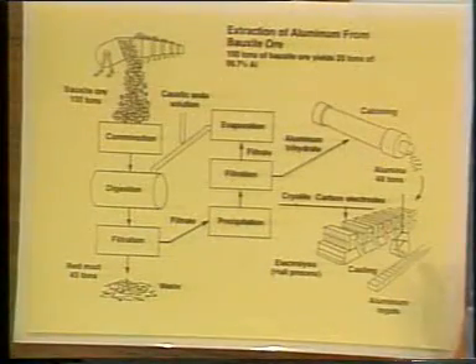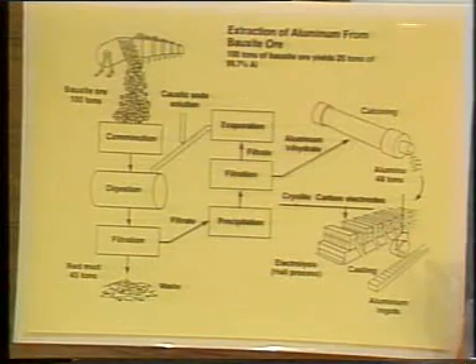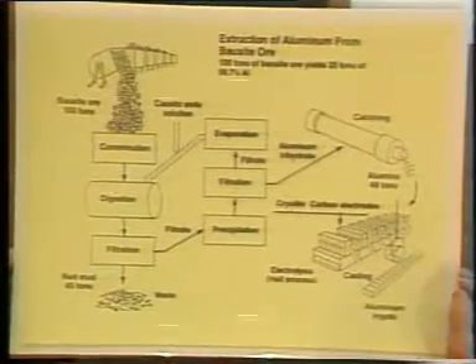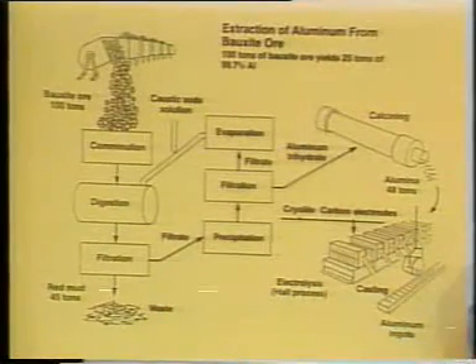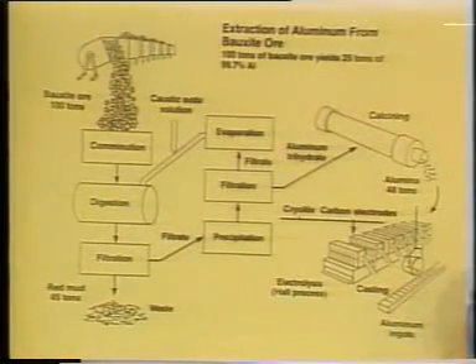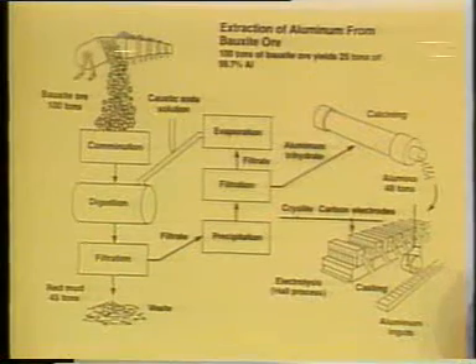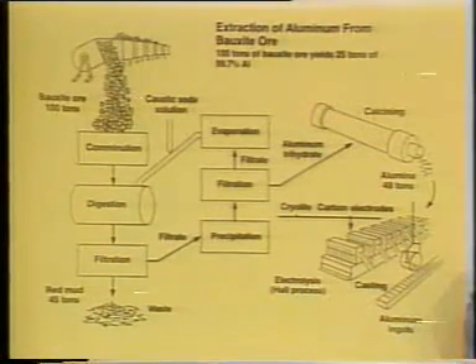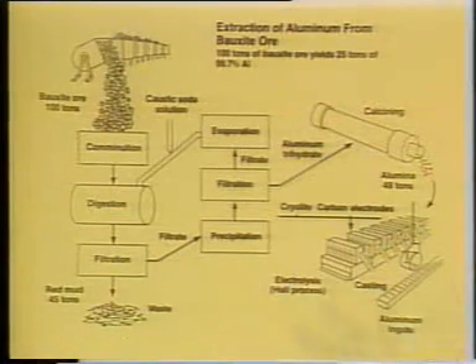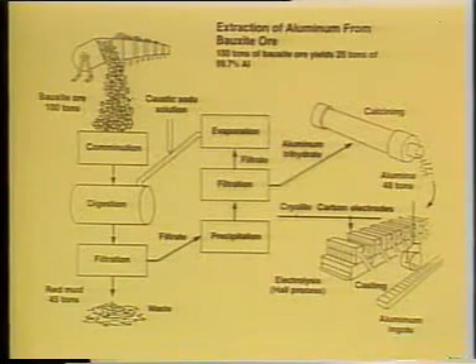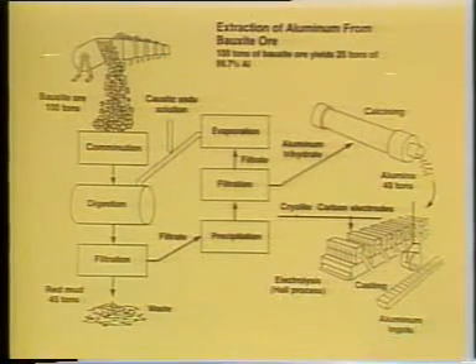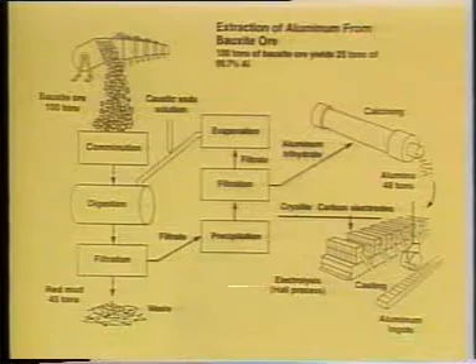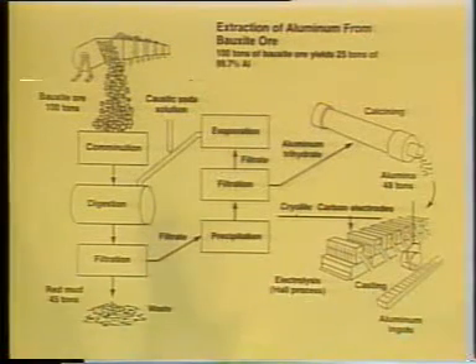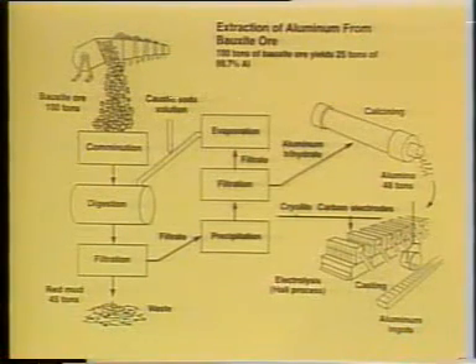Charles Hall did get the patents on the thermal electrolytic or pyroelectrolytic process for producing aluminum. But prior to that, aluminum was being made, particularly in France, and it had been identified some 40, 50 years before that. But we had a hard time developing it into a metal. That's because the heat of oxidation of aluminum is very, very high, extremely high. It forms the oxide so readily that it's hard to break that bond with the oxygen. We just cannot do that.